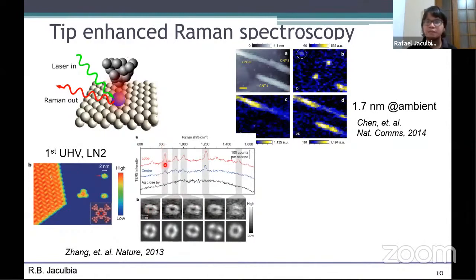Because, for example, one Raman mode only vibrates the outer benzene rings, or one Raman mode only vibrates the inner benzene rings, the signal should only come from the inner part of the molecule or just the outer part of the molecule. Then it was expected that you can differentiate the vibrational modes from the Raman map. But in 2013, although this is the first report of that, they tried a really single molecule, just one molecule in a 3x3 nanometer area. They could detect the Raman signal, but unfortunately, they couldn't resolve the different vibrational modes. So it was a good result, but it's not complete.